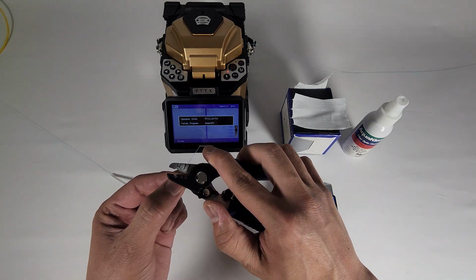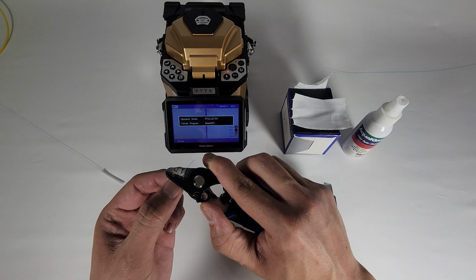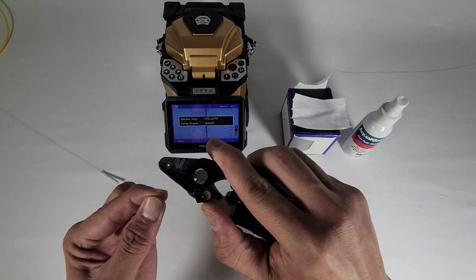Now remove 40 to 60 millimeters of the colored 250 micron soft peel acrylate from your fiber using the center 125 micron or B opening on the polymer strippers in a singular pass.